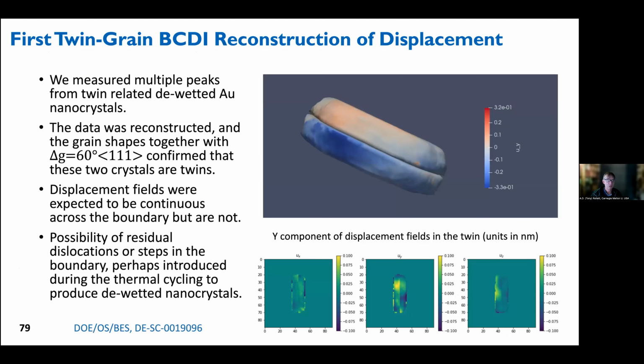And then within the last 9 months or so, we're able to find pairs of twin-related crystals and do the reconstruction from a pair of twin-related crystals. And when you have an annealing twin, that's actually rather convenient, because that 60-degree misorientation about a 111 axis is very much the absolute minimum grain boundary energy that you can have, which means that that grain boundary tends to be very flat, reflecting that deep minimum in the energy surface. But that gives you a piece of prior information, if you like, about the shape of both of those crystals.